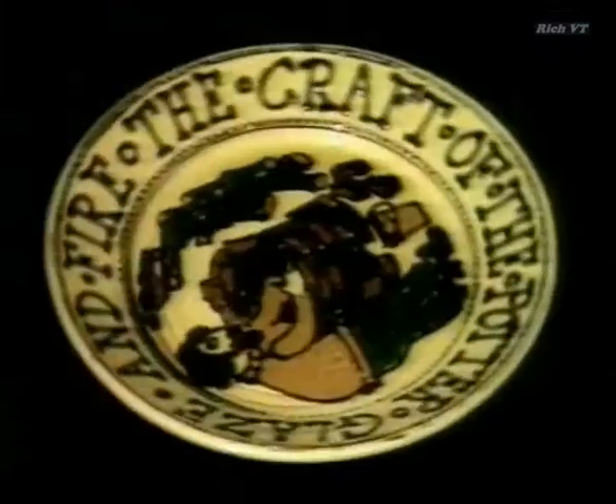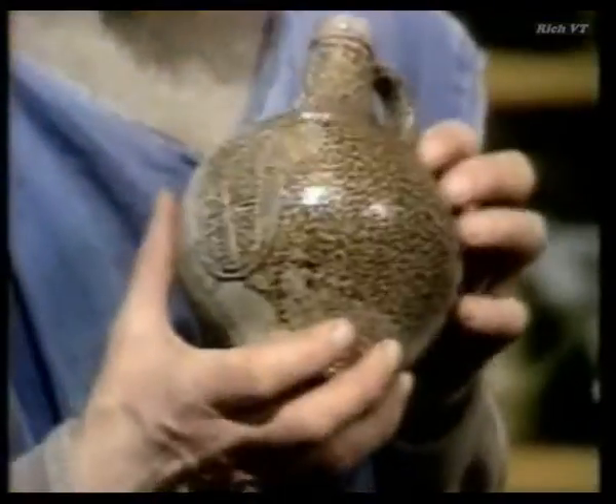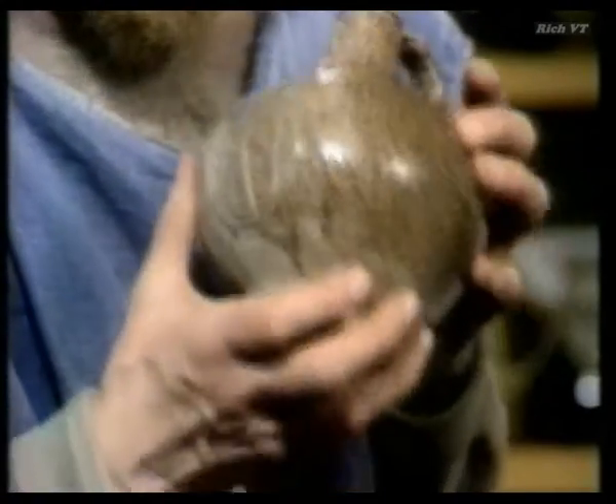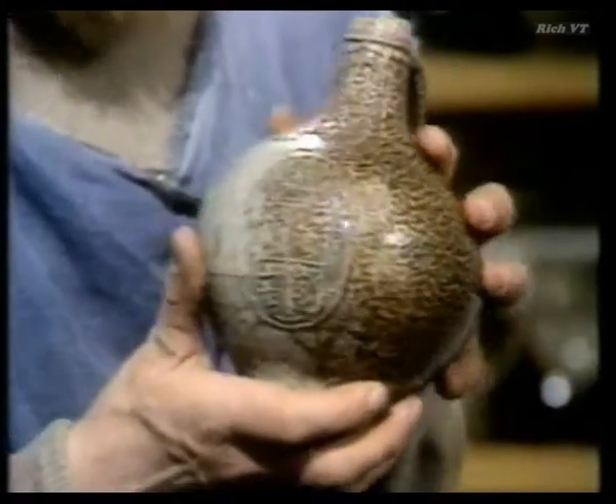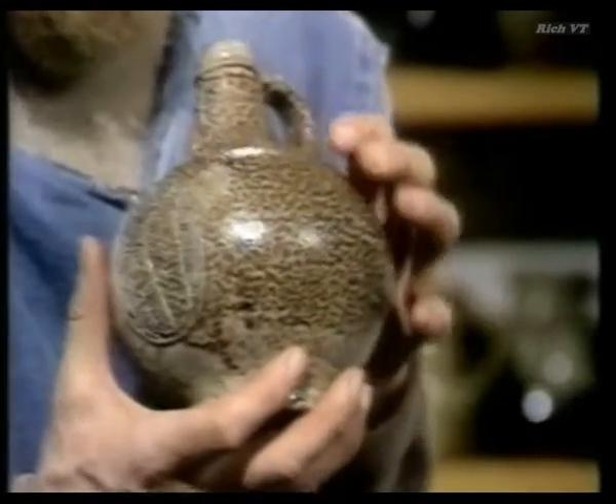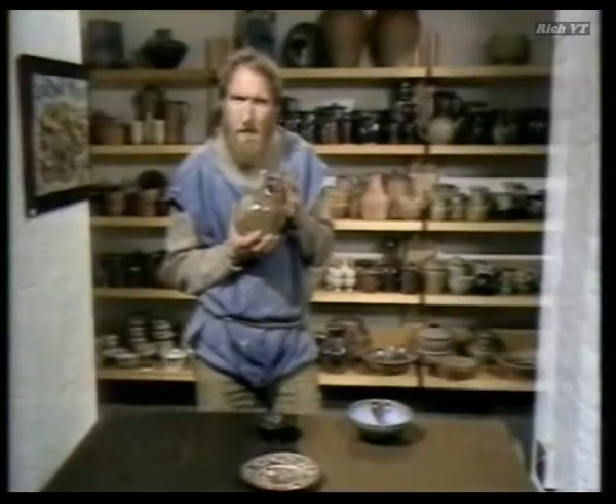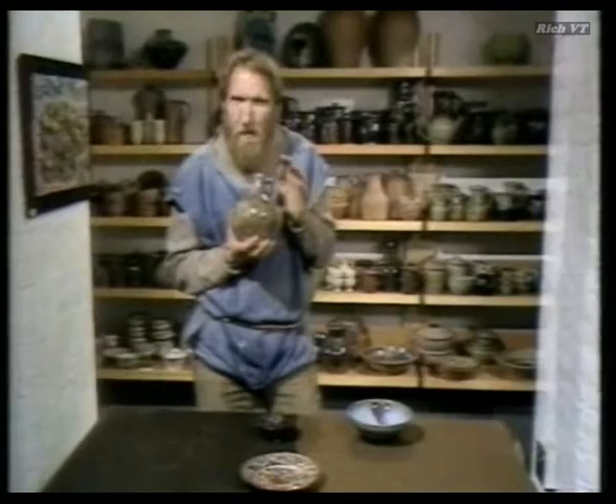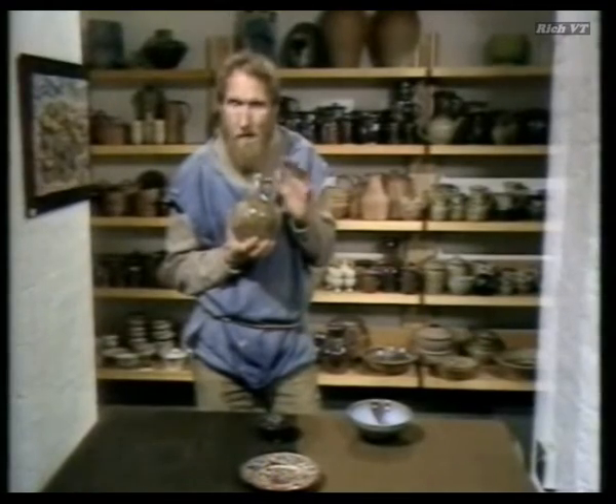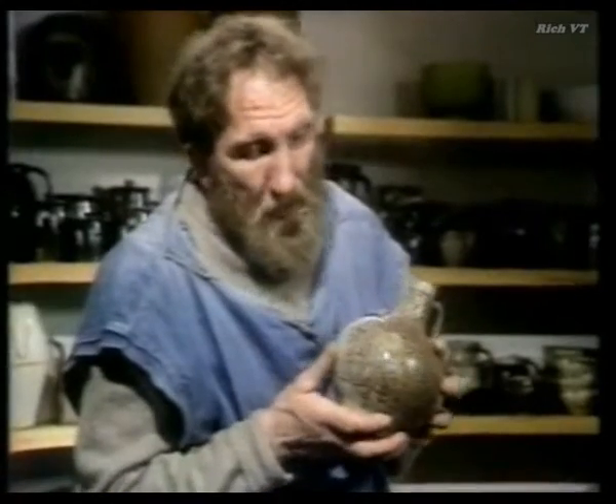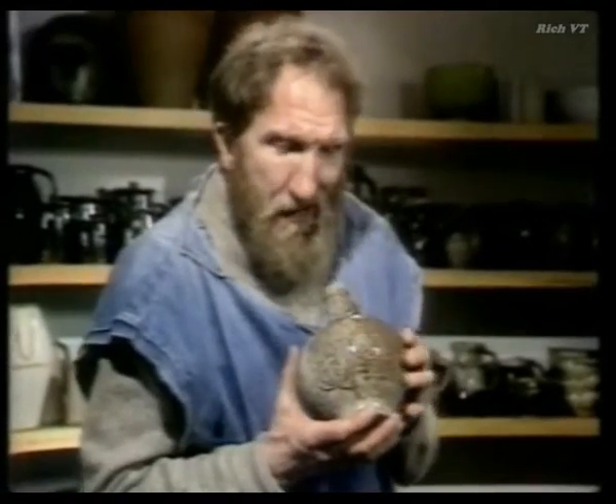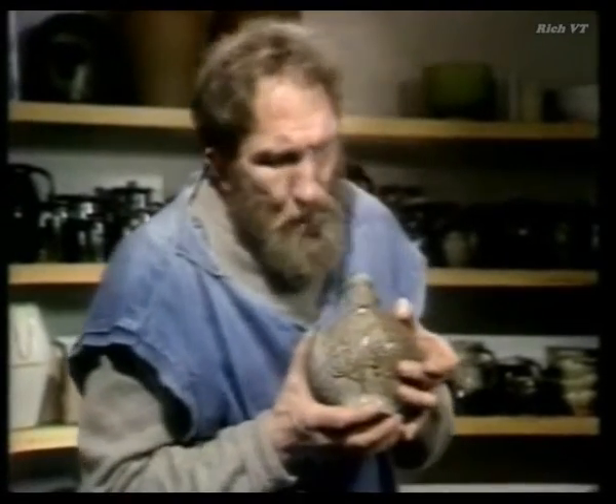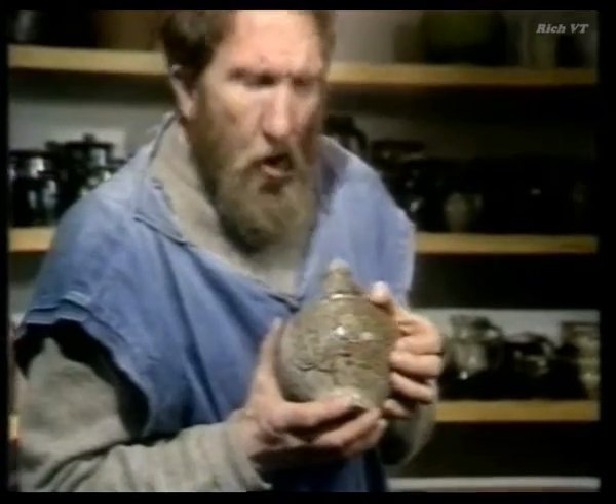If we look now at some ancient pots, we'll see how some of these faults have been used to very great aesthetic purpose. To take an example, this may look like crawling, but what's actually happened to this little pot, probably an English 17th century bottle, is that it's been salt glazed. That means that at the height of the stoneware firing, salt has been thrown into the flames of the firebox. The salt volatilizes, combines with elements in the clay, and forms a glaze. It goes everywhere, forming this brown, mottled, slightly orange peel effect.